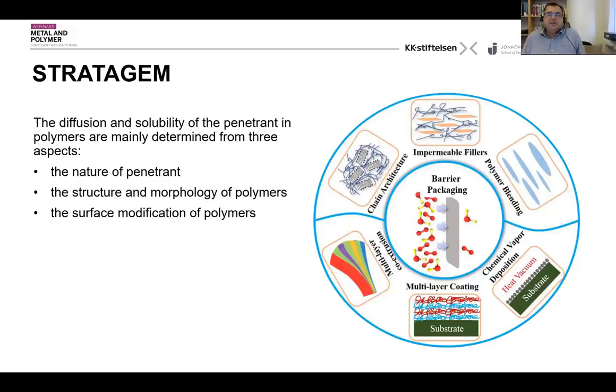Whereas crystalline polymers provide a treacherous path for the permeating species. The permeating species have to play around these crystalline regions in order to surpass them. So one way of improving the barrier properties of the polymers is to increase the percentage crystallinity in our polymers. For example, low density polyethylene does not have barrier properties as good as high density polyethylene, because high density polyethylene is more crystalline in nature.